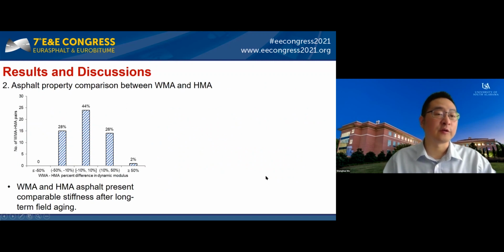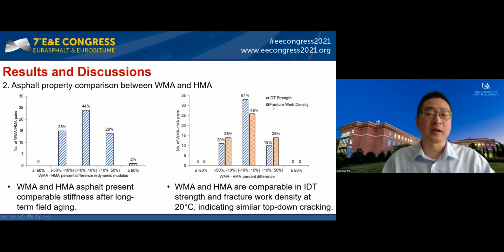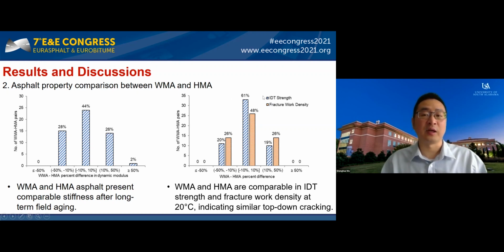So the next one, we are going to focus on the asphalt mixture properties comparison between HMA and WMA. This figure shows the number of WMA and HMA pairs with respect to the percent differences in the dynamic modulus. You can see the majority of the WMA and HMA are pretty much comparable in terms of stiffness. The second figure shows the IDT strength and fracture work density comparison for the HMA and WMA. Again, we can see the majority have very similar material properties here, indicating HMA and WMA show similar top-down cracking resistance.